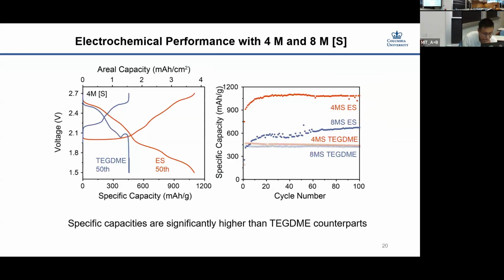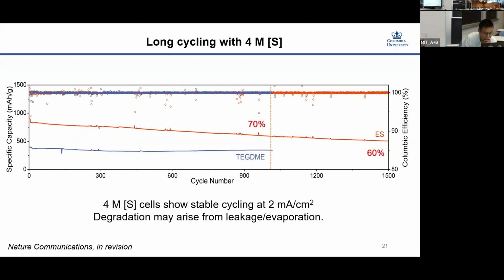So 1 mole shows a high capacity, but if you think about the mass of the electrolyte, it's actually not a high density. So you actually want to increase the concentration of sulfur to at least 4 mole or 8 mole. So we further try cells with 4 mole and 8 mole of sulfur. You can see that with 4 mole sulfur, you can still get over 1,000 mAh per gram. And with 8 mole, it can reach 600 to 700 mAh per gram, and both are much higher than the TEGDME control samples.